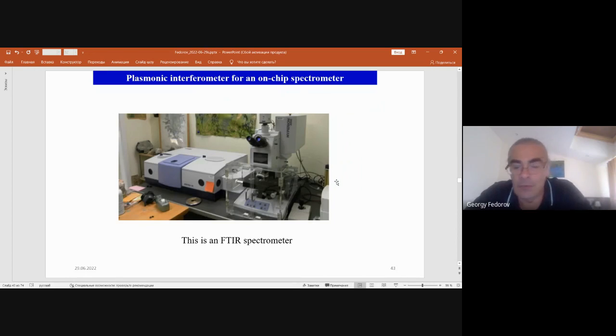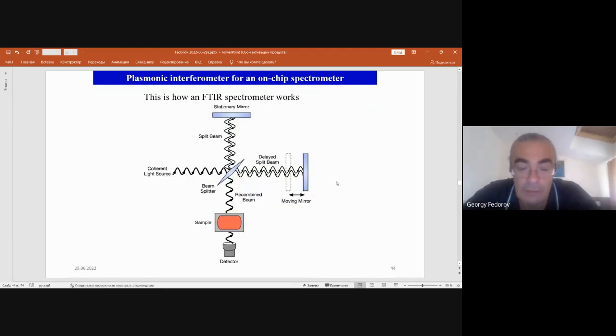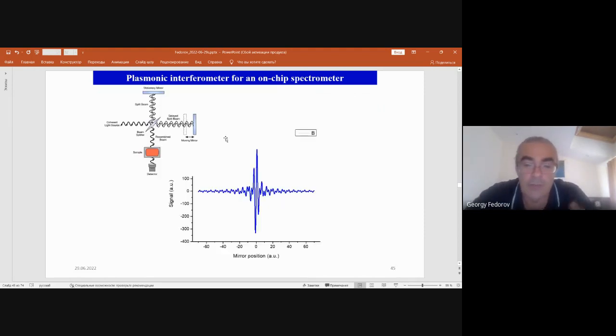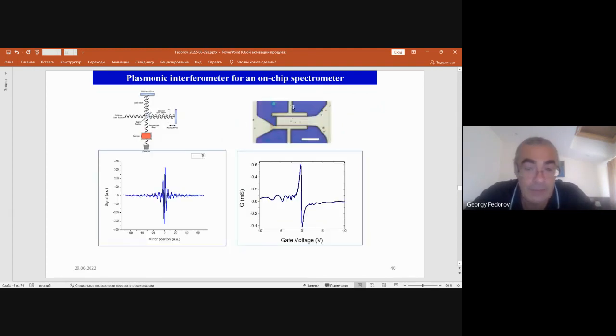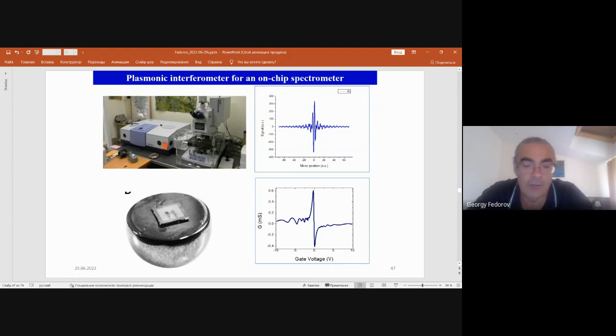it may be used for on-chip spectrometry to replace the bulky Fourier transform infrared spectrometer, of which the principle is that you move a mirror, and in our case we tune the effective refractive index of the medium between these mirrors. And in a Fourier transform device, we move the mirror and get this signal as a function of position of the mirror. And here we tune the phase velocity and get this signal as a function of gate voltage. Here you can do a simple Fourier transform. Here you cannot do a simple Fourier transform because the system is not very linear, but I believe that we can calibrate it in order to get a very compact on-chip spectrometer out of our good graphene.